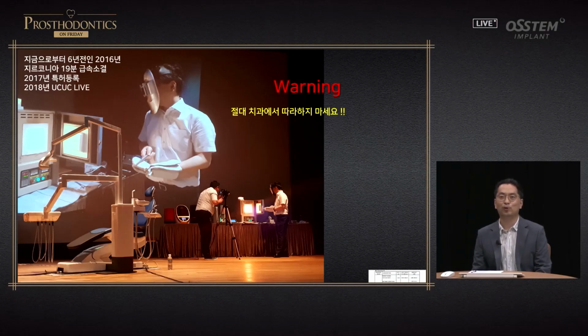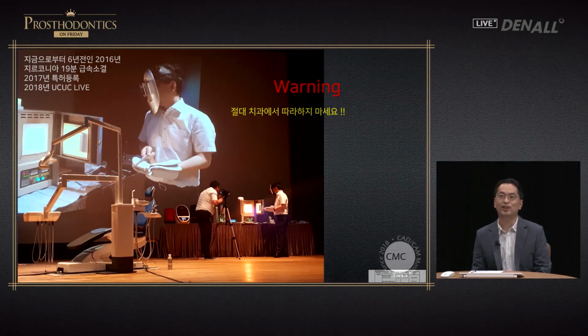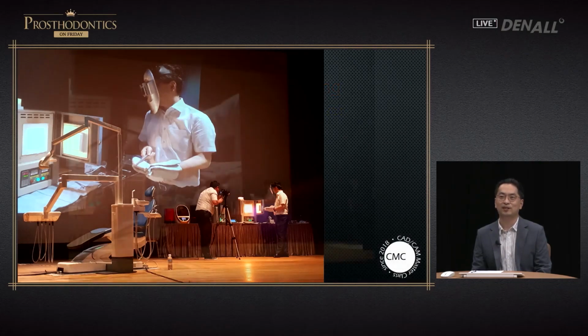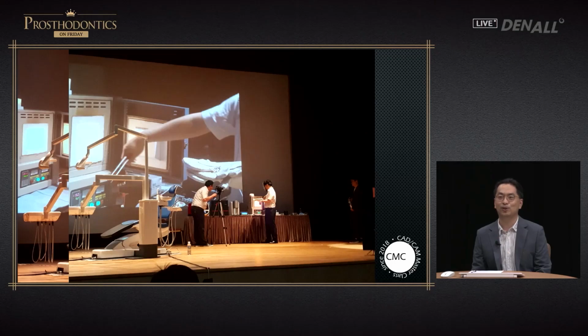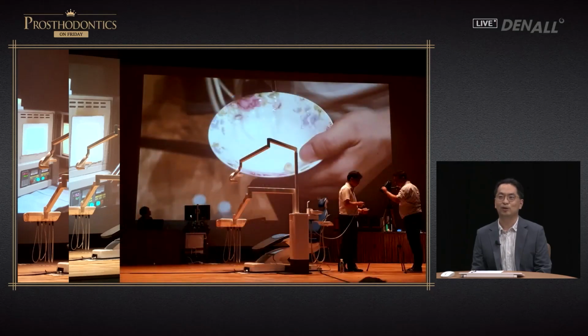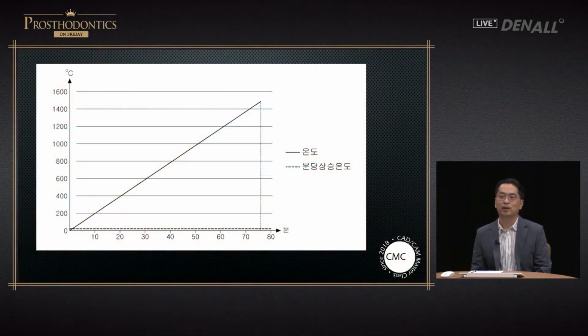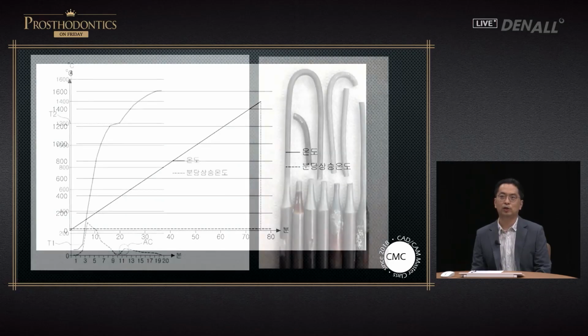You can see that the furnace is opened at 1,500 degrees. I put in the zirconia at 1,300 degrees. And then I pull it out. This is a dangerous process. You should not try this at your dental clinic. At the time, based on my passion and effort, I was able to succeed in zirconia sintering within 19 minutes. It takes over an hour for the furnace to go up to 1,500 degrees. In order to reduce such time, what should we do?